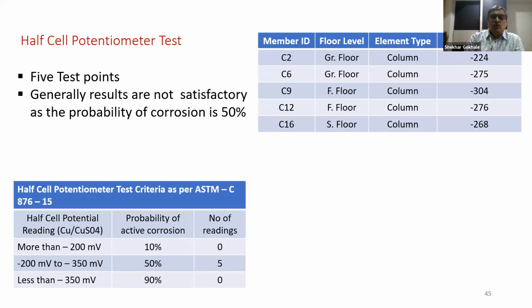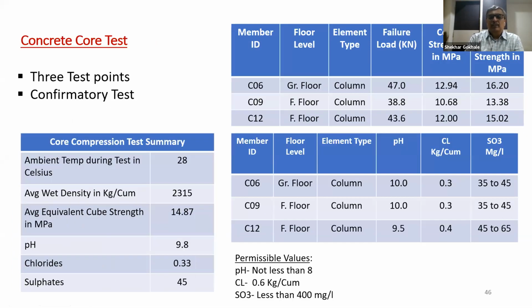So to conclude, we carried out concrete core test at 3 samples, at column number 6, 9 and 12, at ground floor, first floor and first floor. We took the results, and the equivalent cube strength given is 16.2, 13.38 and 15.02, which is averaging to around 14.87 Newton per millimeter square. So this is more or less equal to the design concrete strength the designer must have considered at the time of construction of the building, because in 1972 for a ground plus 2-story structure, designers used to take M15 grade of concrete only, nominal mix concrete. So this is more or less equal. With some standard deviation we can apply, and we can consider the concrete strength is reasonable.